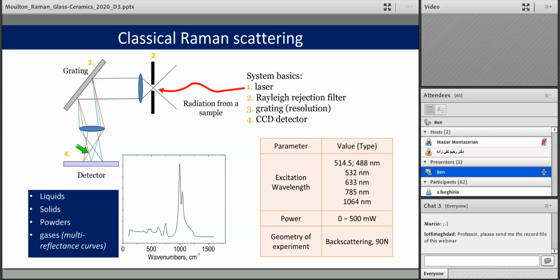Some of the most common lasers used are blue lasers like the 488 or 515, down to red lasers like the 633, or infrared and near infrared lasers such as 1064. Powers range from 0 to 500 milliwatts. As you go to longer wavelengths, we'll see that the Raman response decays, so you need to increase the power to make up for this lack of response. And you can do several different types of geometry. The most common for silicates and ceramics is the backscatter geometry.